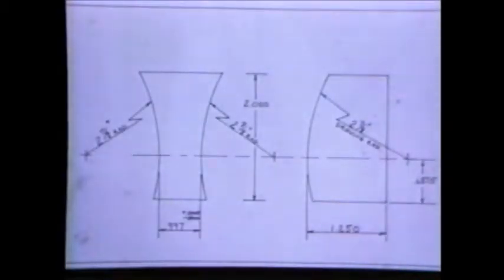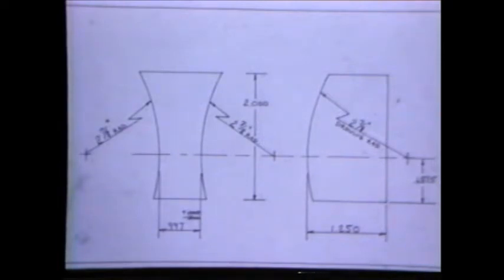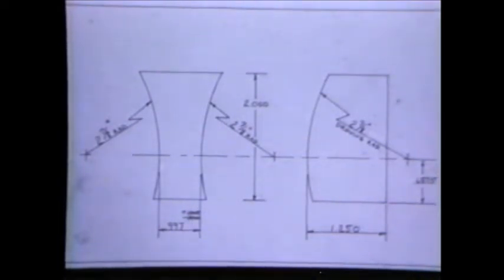This end block print is of a pretty typical design. The draw radius is thrown off center to allow sufficient top opening to accommodate the entering flat stock. There are also many variations of this design. Some blocks are designed with actual angle and bearing forms, which make them more like solid dies, but also more difficult to fabricate and maintain. Note the thickness of the block. Increasing this thickness to 1.5 inches or even 2 inches, particularly in side blocks, improves the strength of the carbide to help prevent breakage.